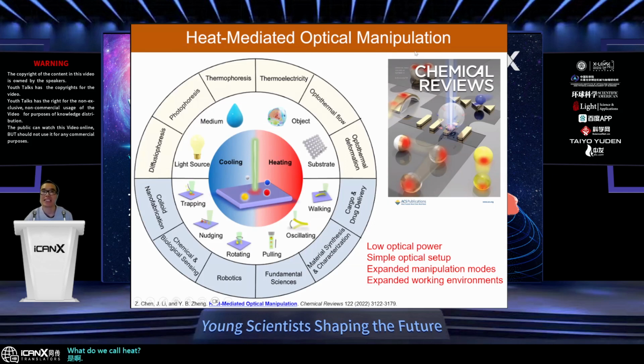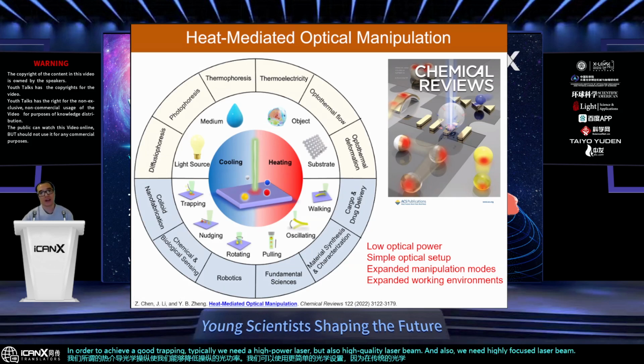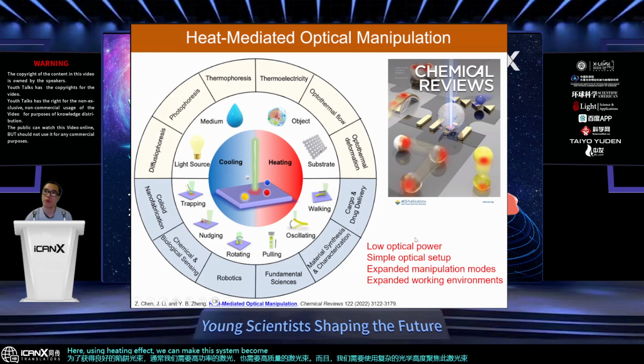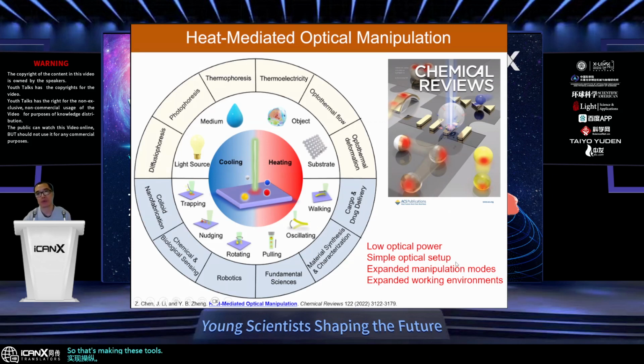we're able to show what we call heat-mediated optical manipulation, which enables us to reduce the optical power for manipulation, and we can use a much simpler optical setup. In traditional optical tweezers, in order to achieve good trapping, we typically need a high power laser, but also a high quality laser beam, and we need to highly focus this laser beam using complicated optical systems. But here, using heating effects, we can make this system really simple. We can even use incoherent light, white light, or even the laser pointer typically used for presentations to achieve the manipulation. That makes these tools accessible to more researchers beyond those labs with sophisticated systems.